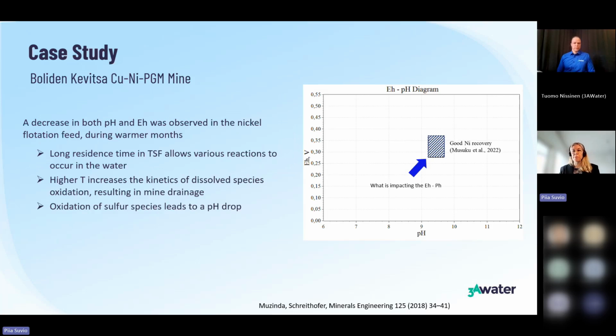Okay, let's look at the Eh-pH diagram a little bit here. So here is the good nickel recovery as they found in Kevitsa. It's quite a small window that the Eh-pH has to be in order to get a good nickel recovery. What they discovered in the warmer months was a decrease in both the pH and the Eh, so the redox potential, in the nickel flotation feed. Once they investigated this further, they realized that the long residence time in the tailings storage facility, so this is a tailings dam, allows various reactions to occur in the water. And this is a sulfide ore, so the higher temperature increased the kinetics of the dissolved species oxidation, and this was resulting in acid mine drainage, which is a very low pH acidic phenomenon. The oxidation of sulfur species then led to this pH drop.